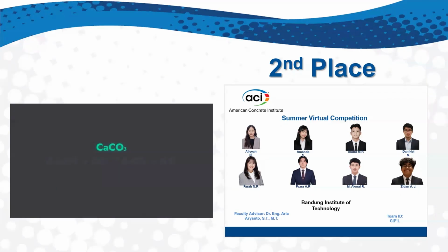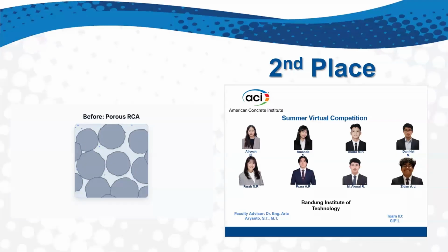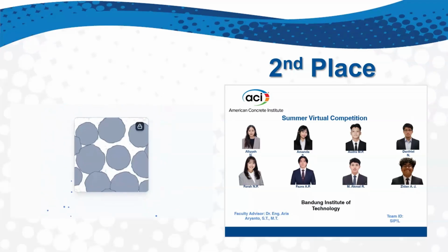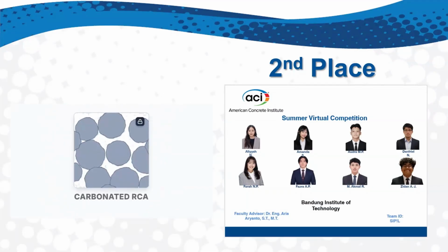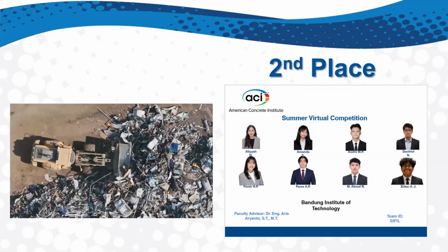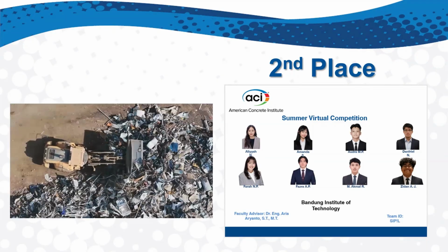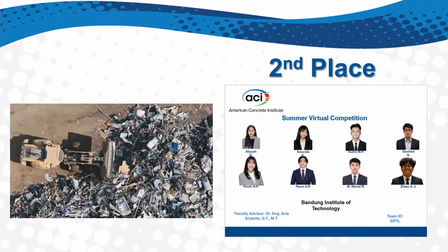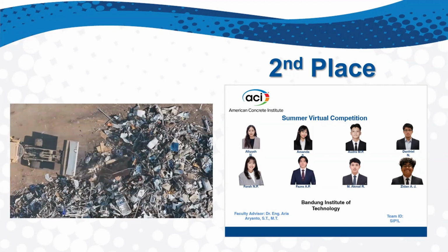The calcium carbonate, or limestone, acts like a natural filler. It plugs up tiny holes and packs the weak spots tightly, making the material much denser. Instead of the gas escaping back into the air, it gets trapped and turned into solid minerals inside the recycled concrete aggregate. This makes the surface stronger, keeps water out, and results in what we call carbonated RCA. So this is not 2 separate ideas, it is one simple loop. Recover the RCA, cure it with carbon dioxide, then reuse it in new concrete.